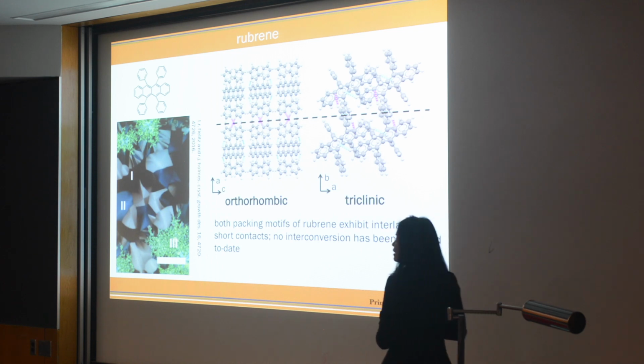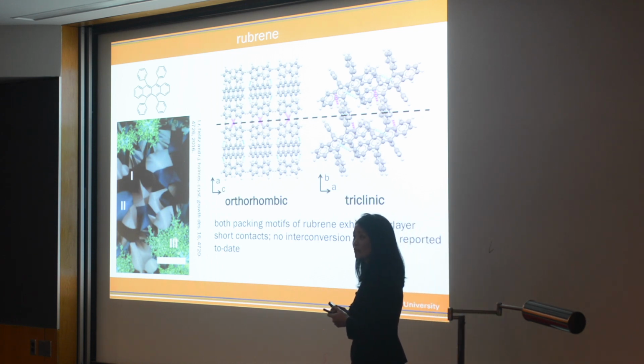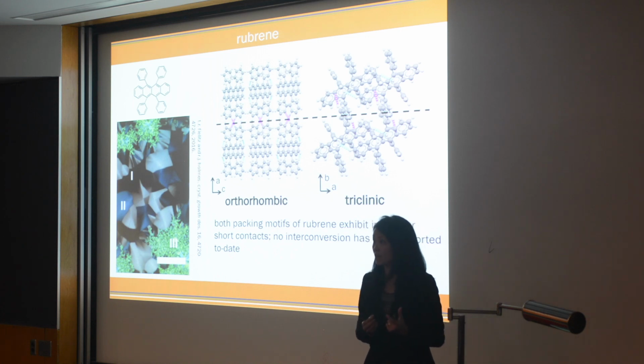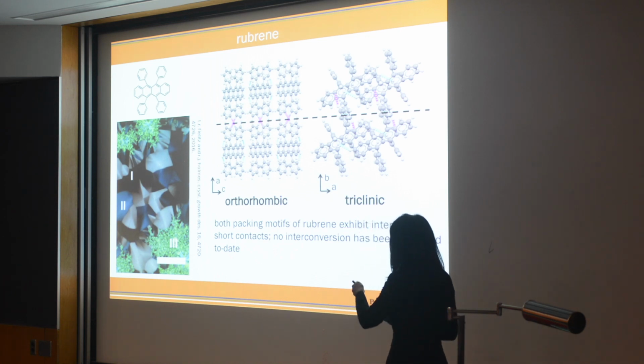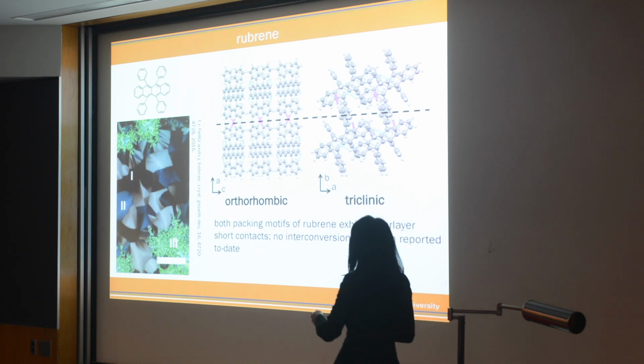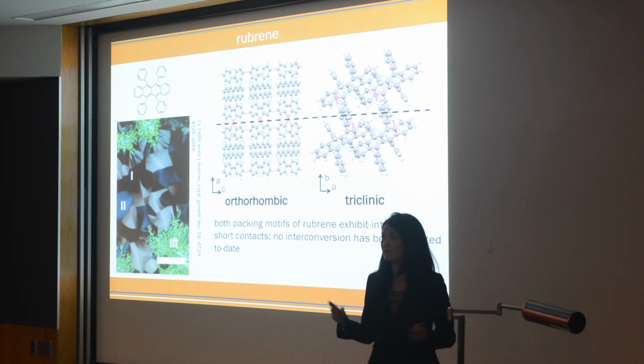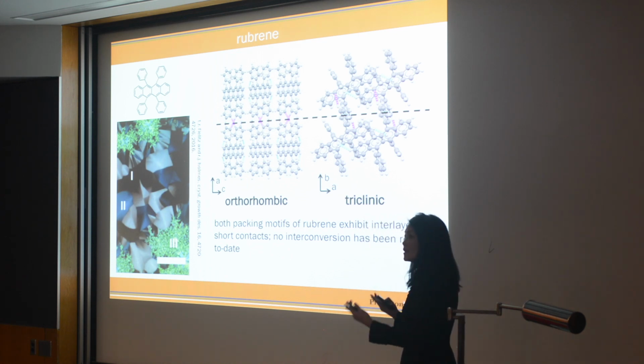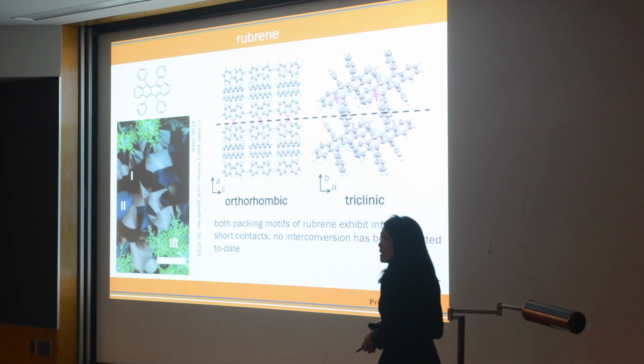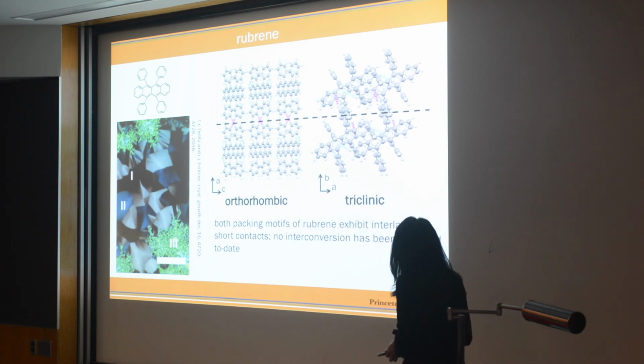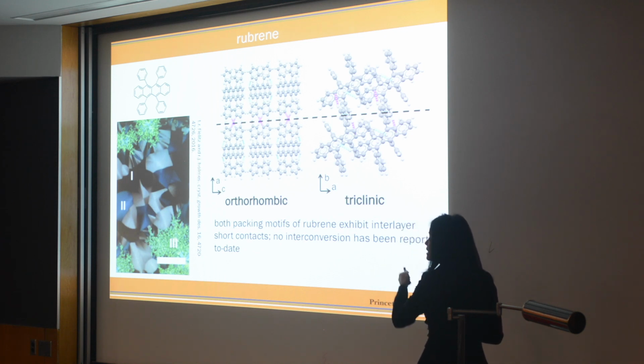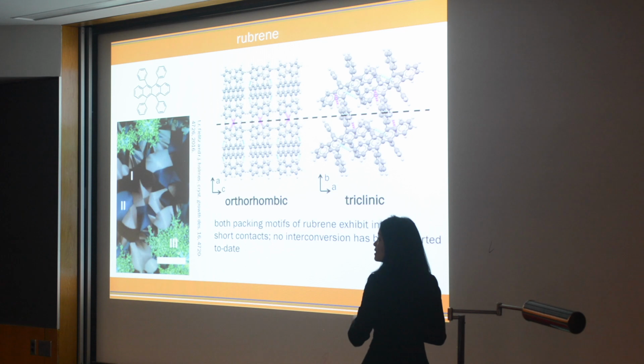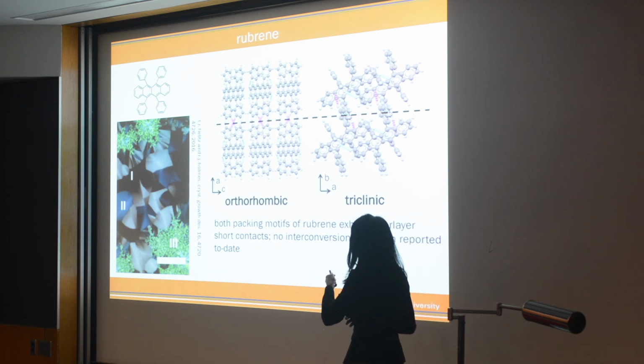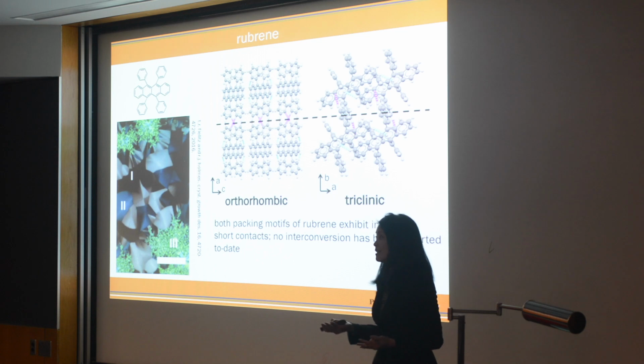So this is rubrene. And I've shown you examples of rubrene, and I've told you that rubrene has two crystal structures, the orthorhombic and the triclinic. It's interesting in this paper and many other papers that rubrene can exist in both polymorphs in thin films, and they appear to be stable. They don't interconvert. You can have it sit there forever, and it stays in coexistence forever. And we believe that perhaps not coincidentally, you see a lot of these short contacts between the layers of both the orthorhombic and the triclinic structure. And because these short contacts are present, they're just kind of there, right? It stabilizes these two polymorphs.